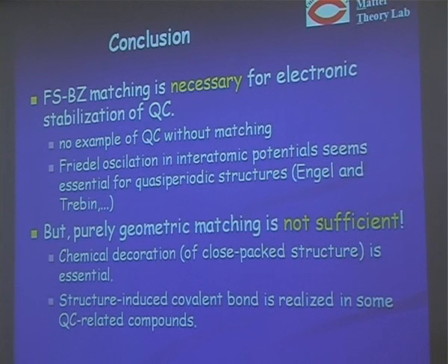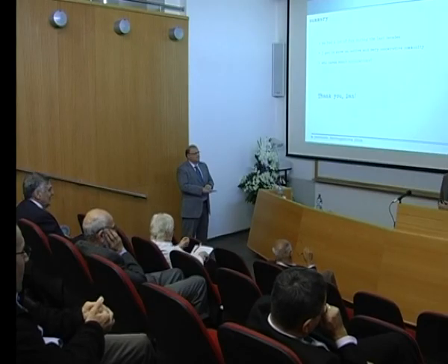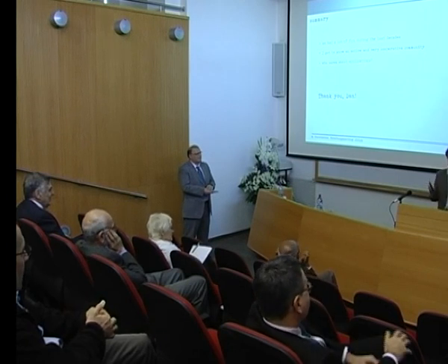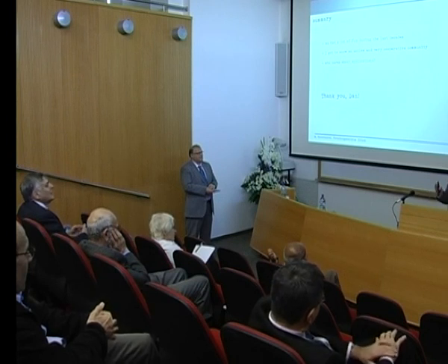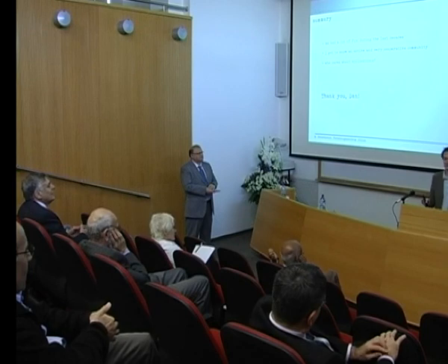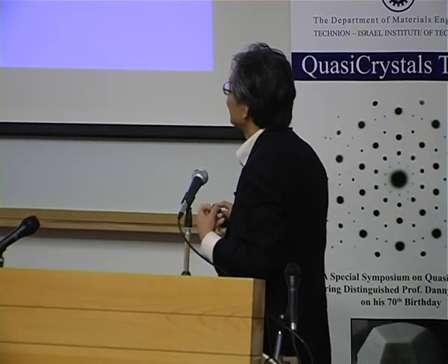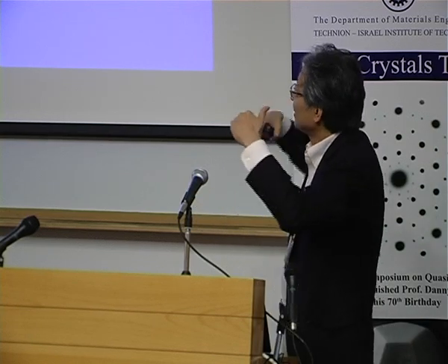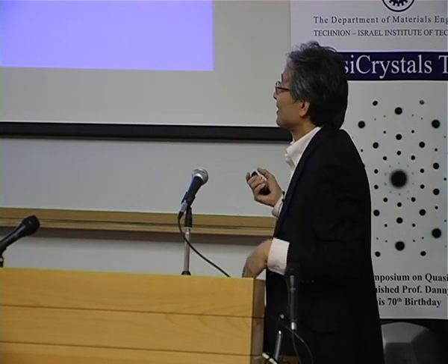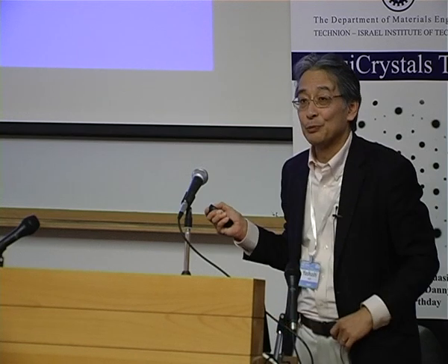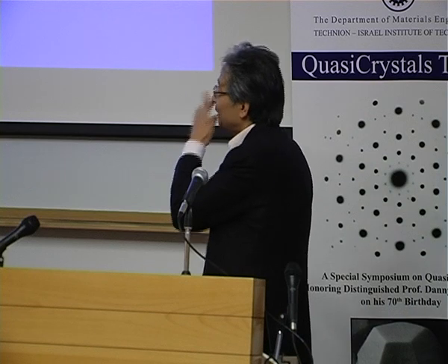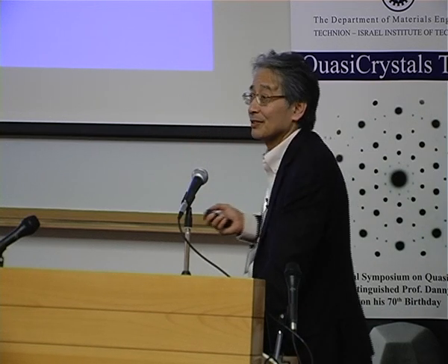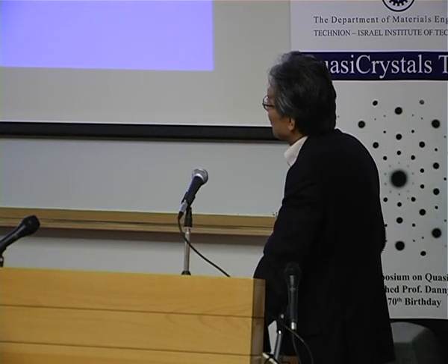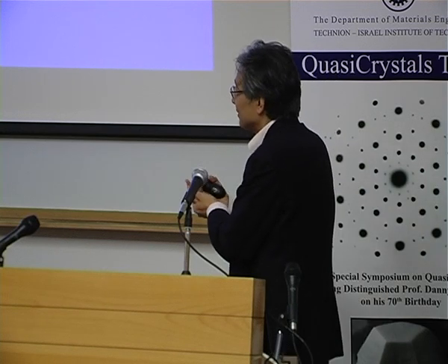Fermi sphere Brillouin zone matching is necessary for electronic stabilization of quasicrystals, of course, because we have no example of a quasicrystal without matching. And also, the Friedel oscillation in the interatomic potential seems very essential for our quasi-periodic structure. I will not discuss it in detail, but the formation of the structure favoring the oscillatory interatomic potential is really consistent with the Fermi sphere Brillouin zone matching. But I want to stress that purely geometric matching is not sufficient. And here we show the chemical decoration is essential. Structure-induced covalent bond is realized in some quasicrystal-related compounds.